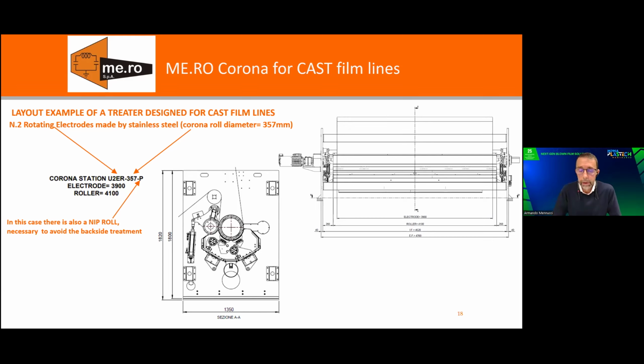And the corona roll, of course, is much bigger in diameter than the corona rolls we use for blown film lines. It's vulcanized silicone rubber, but it can also be coated with ceramic, isolated ceramic, in alternative. What is important is the corona roll has to be driven with a motorization, and cooled by water. And of course, the diameter must be suitable to allow the big power that is involved to not heat up the surface coating of the roll too much.